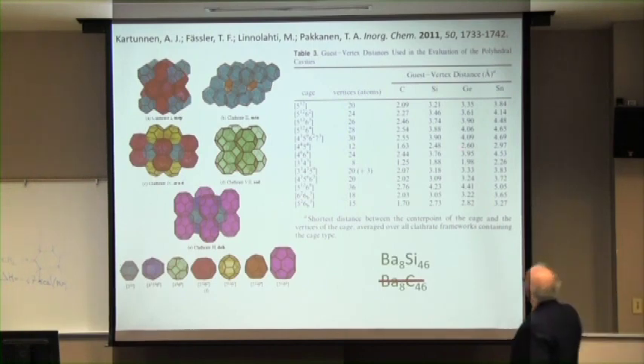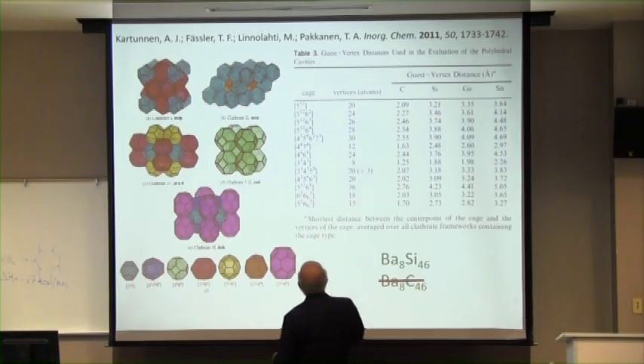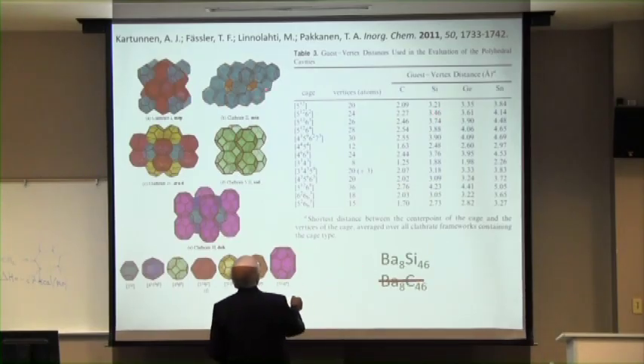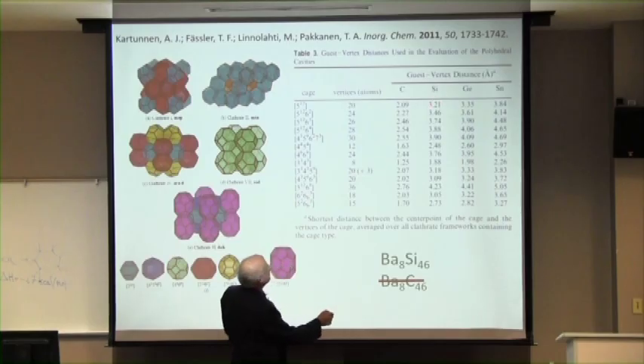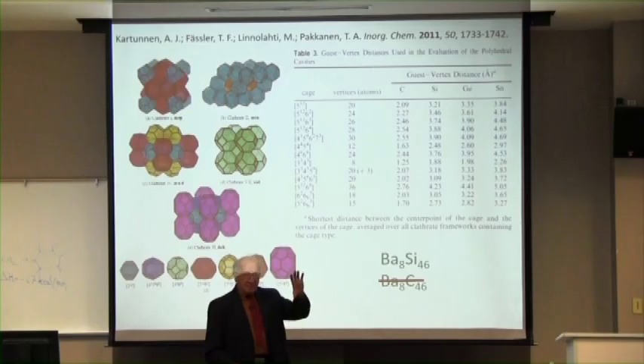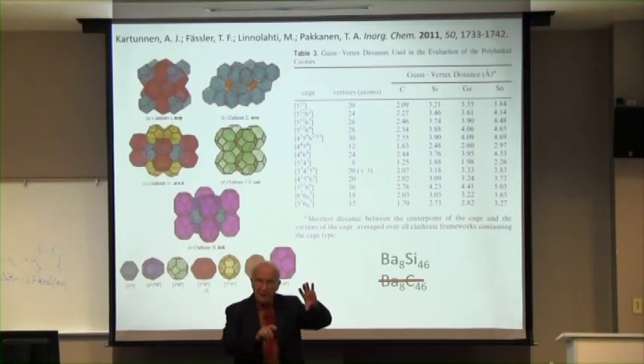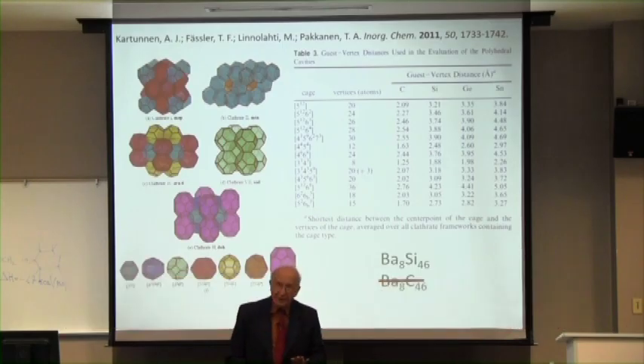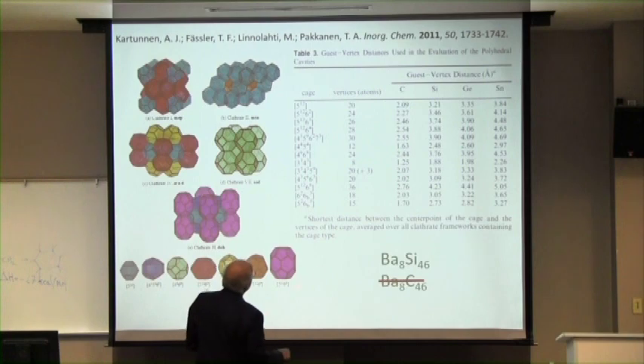And if you take silicon with a silicon single bond distance of 2.35, you find that the center to vertex distance is 3.2. That's pretty big in the middle. That's big enough for barium, as you saw. It's big enough for barium. And barium is pretty big. It's big enough for anything smaller than barium, too. And the same goes for germanium, and look what happens with carbon.